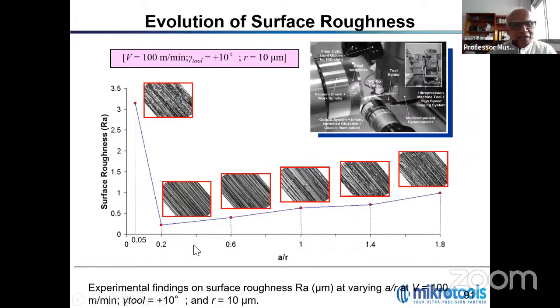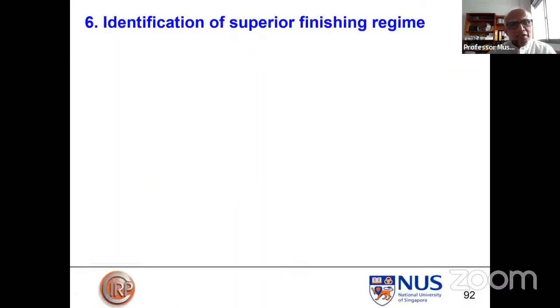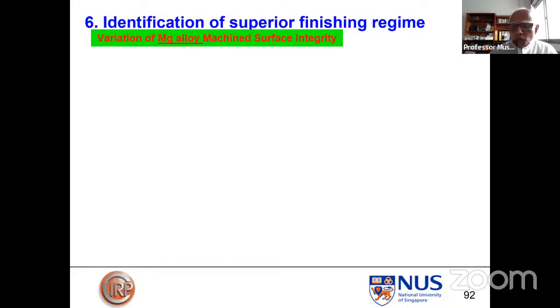Now at A by R 0.25, we get absolutely very clean surface. Beyond that, surface becomes rough. Below that, surface becomes rough. These are all details. But again, we continued.